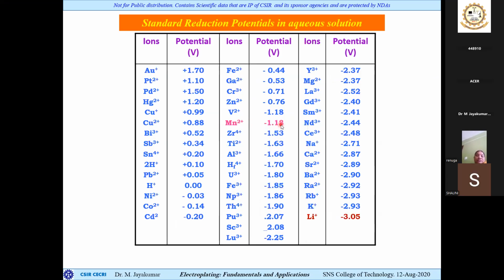So manganese is the last metal theoretically you can deposit. In practice, zinc is the last metal you can deposit because zinc's reduction potential is still negative, but before the water splitting reaction. Okay. And almost all the other metals in the positive direction, it is possible to deposit them by aqueous electroplating. So if I don't have a metal ion which has a reduction potential less than 0.76, it is not possible to deposit in aqueous electrolyte.